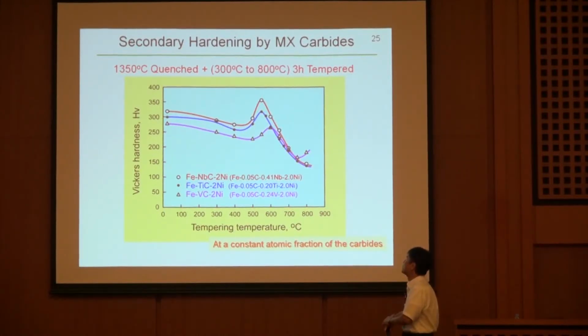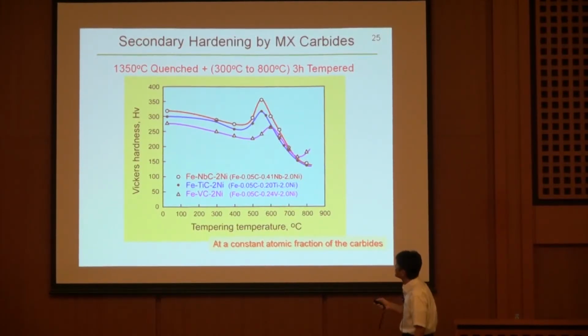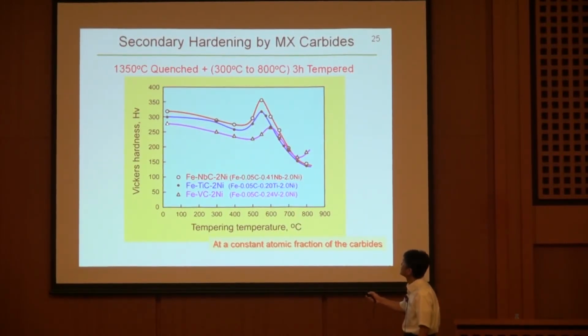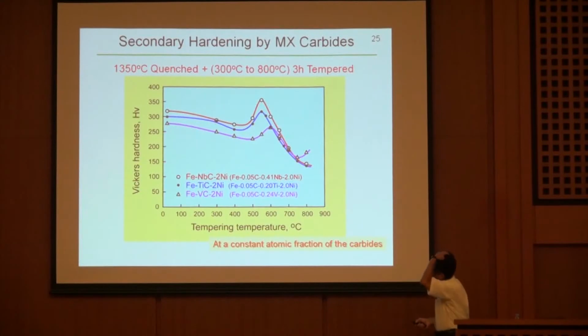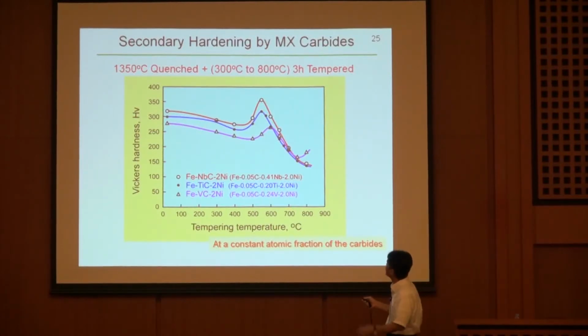This is the matter that you studied in classroom. Because hardness is changing with the tempering temperature, without special carbide, this hardness decreases like this with increasing tempering temperature. However, there is an increase here when the tempering temperature is around 600 degrees C. So this has been observed even in this case. I have to say, I selected the model steel in chemical composition. Okay?